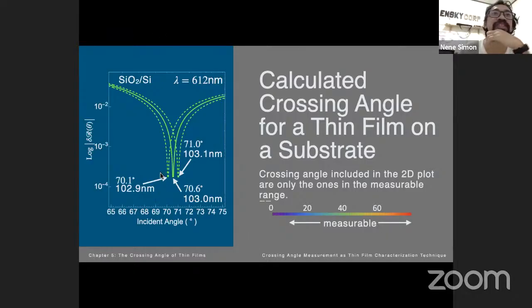So as you can see here, it's sensitive enough to detect sub-nanometer thickness. So the technique itself is sensitive to sub-nanometer thickness. And we can do these calculations for different wavelengths, different refractive index, and different thickness of the substrate.